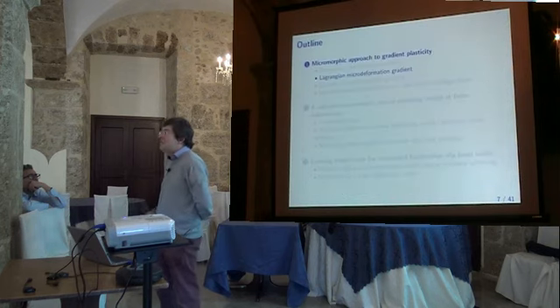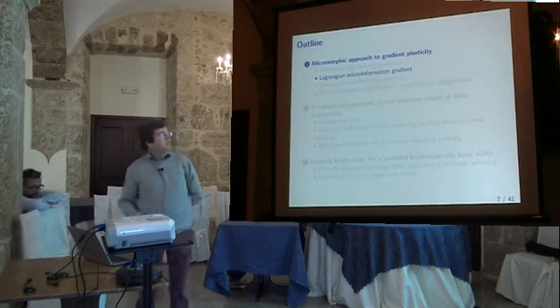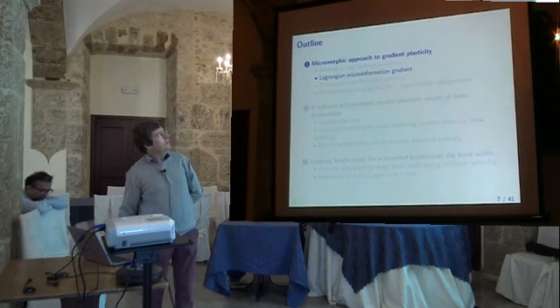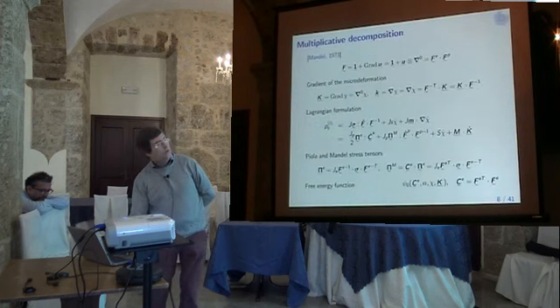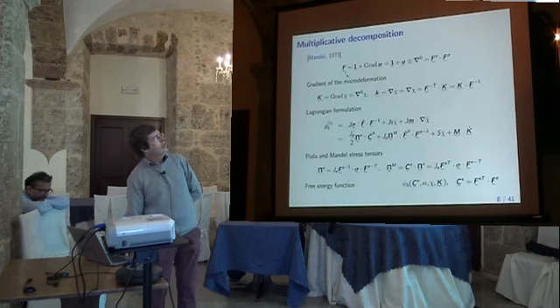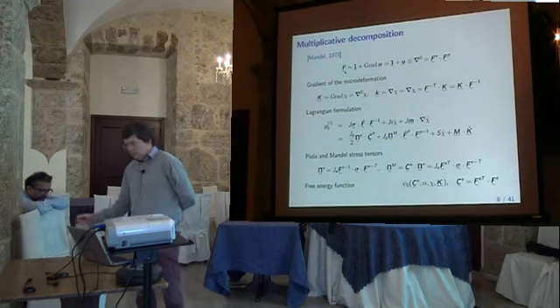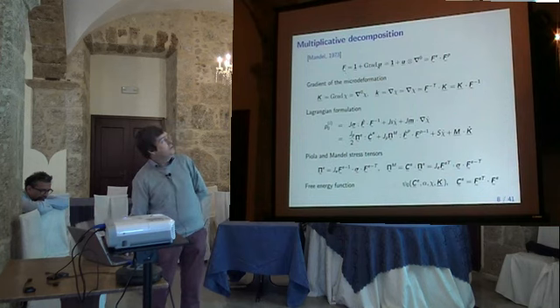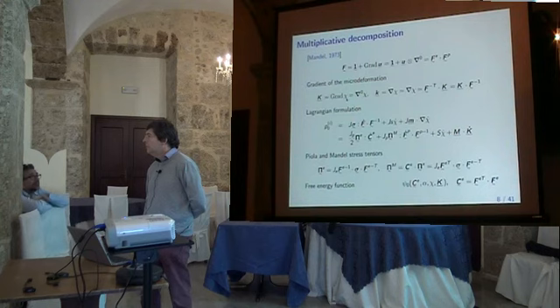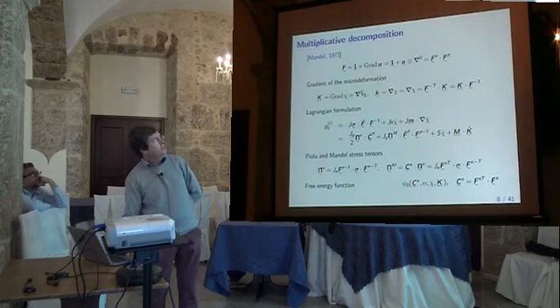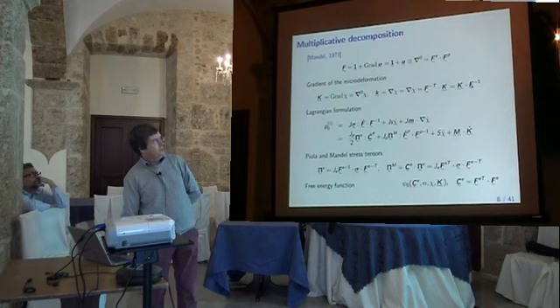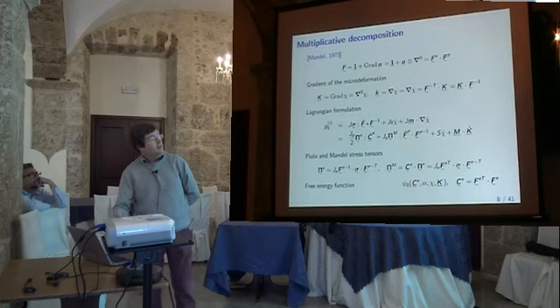But then you have to decide what you put in your constitutive equation. So I propose first to consider the Lagrangian gradient of the micro deformation. So this is a conventional F, you know it, the deformation gradient, standard one. So you take the Lagrange gradient of the displacement here. So I take also the Lagrangian gradient of chi, like this. There is a zero here for the reference configuration. But you could also compute the Eulerian one, and of course there is a relation between them due to the transport by F here.